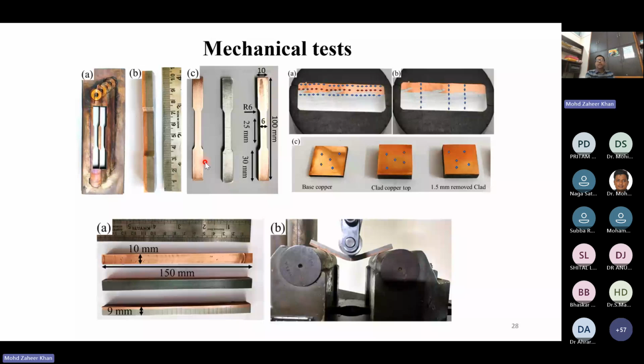Then extensive micro hardness testing was also carried out as per the scheme shown in this figure. So what we did is that on the cross section of the specimen that has been cladded, it was molded and nicely bound, and then indentations were made just below the clad layer, at the interface of the clad and at the interface of the substrate and clad, and near to the top of the clad layer. Similarly, indentations were also made across it, starting from the very top of the clad layer, going through the clad layer, coming to the substrate, and very end of the substrate.